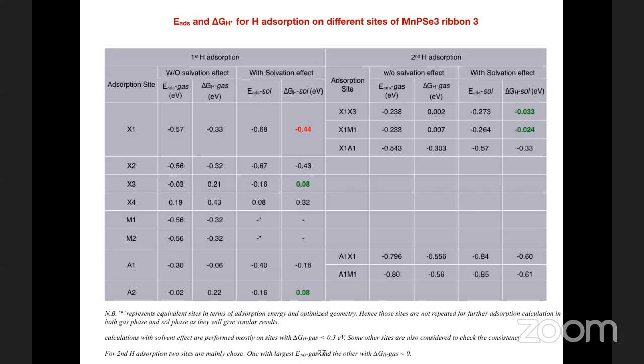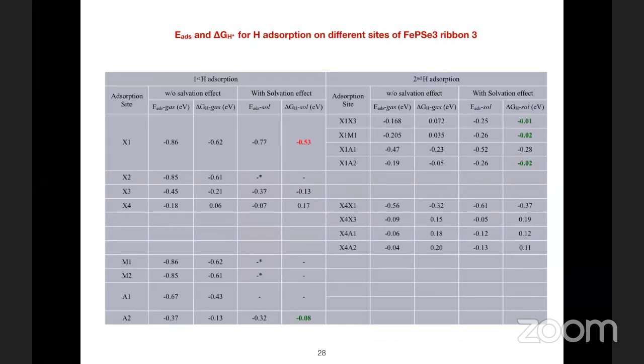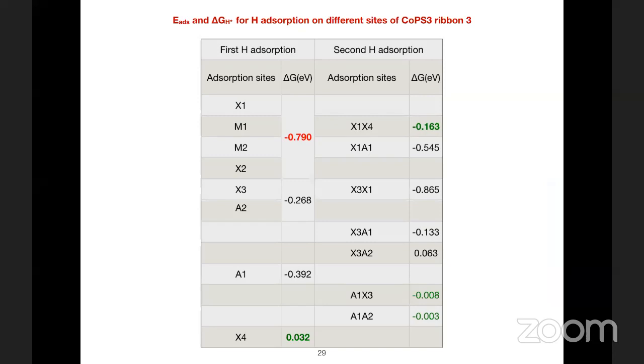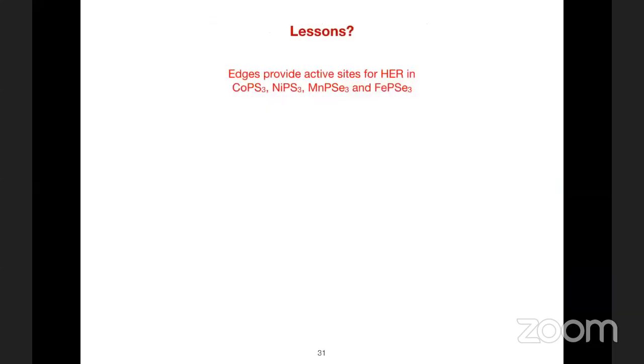This is the MnPSe3 ribbon. X3 or A2 are active sites. X1 has a large absorption free energy, but in presence of one hydrogen at X1, you could have other sites which act as catalytically active sites. So that's how it goes. So the point here is that whether you have low H plus concentration or high H plus concentration, there are sites at the edges which are catalytically active. Okay. So what are the lessons from here?